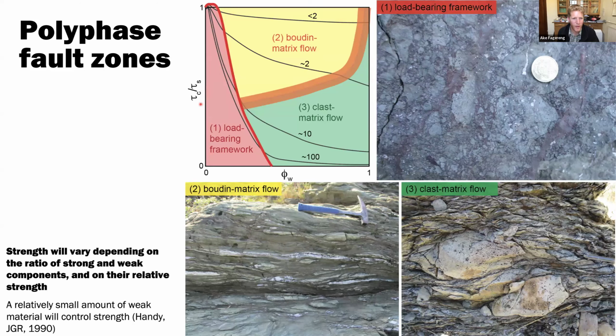So thinking about this in terms of bulk strength, stealing a diagram from Mark Handy back in 1990, if we plot composite strength over the strength of the strongest phase in a two-phase block, at very small amounts of weak material, so phi W is the weak rock proportion, you obviously have the strength dominated by the strong phase. Then if the viscosity ratio or the strength ratio between the materials is very small, then adding the weak rock doesn't do very much. Whereas if the strength difference is large, so a factor of 100, then it seems to be about 20 to 30% of the weak material that makes it interconnected, and then that controls strength.